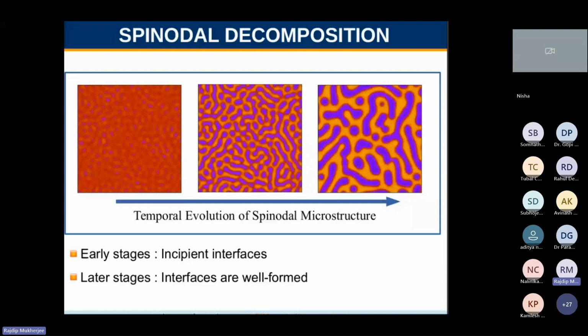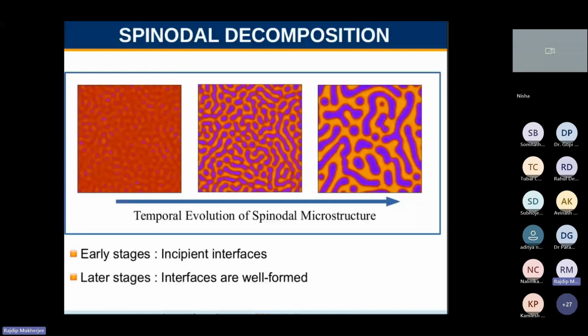In glasses, say borosilicate glass, this spinodal decomposition is observed. Silica melts at a very high temperature, above 1700 degrees centigrade. But when it decomposes, it decomposes into a boron-rich phase and a silica-rich phase. And if you leach out the boron-rich phase, you get a porous microstructure, which can be used for catalysis applications as well. So this spinodal decomposition is very important for metallurgical, polymeric and glass systems, in all these systems where the material decomposes into two defined phases.